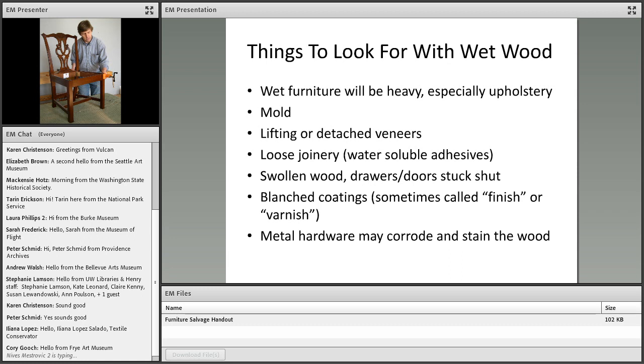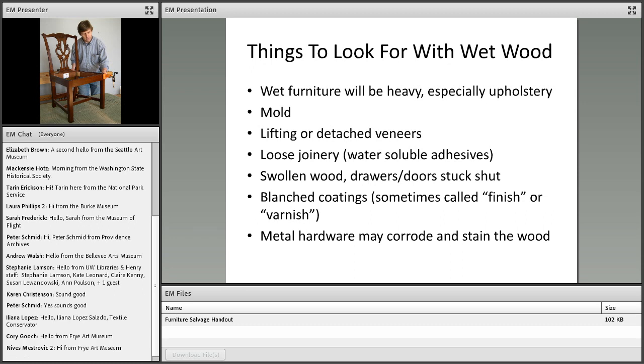They can become deformed as they get wet or as they dry out. And as we just saw, wood will expand when it gets wet and this can cause doors and drawers to get stuck shut. Blanching of coatings means that the water has penetrated into the finish and caused a disruption of the finish, which impairs the transparency of the finish and it turns white. I'm going to show you some examples of these conditions and then we'll look at salvage procedures.